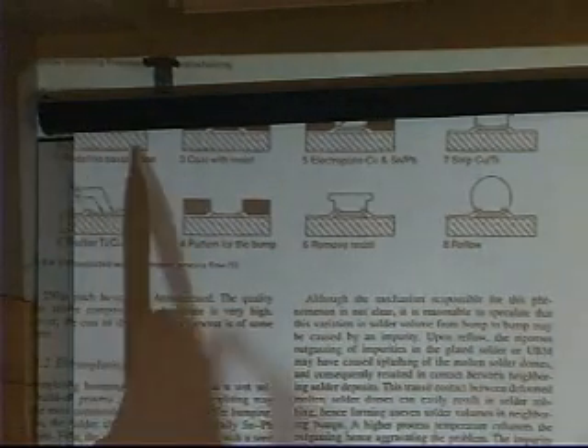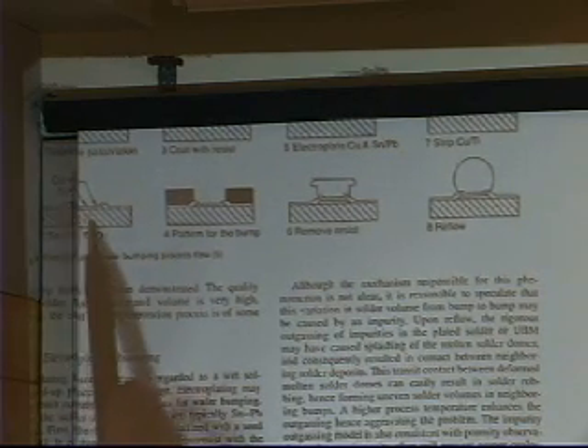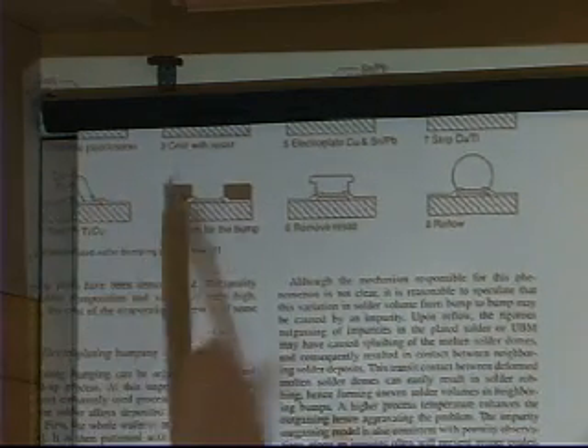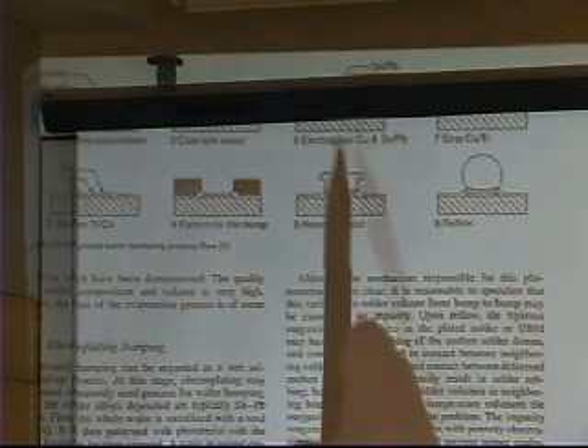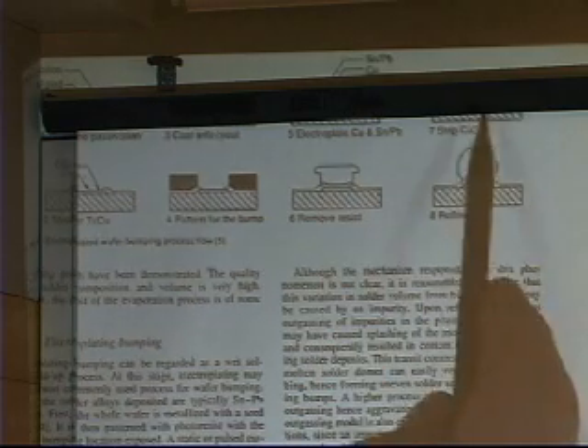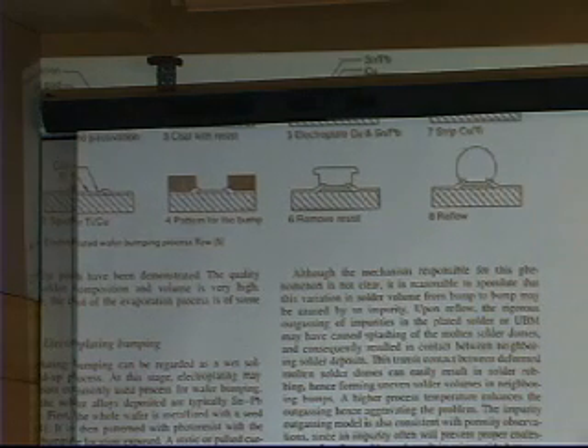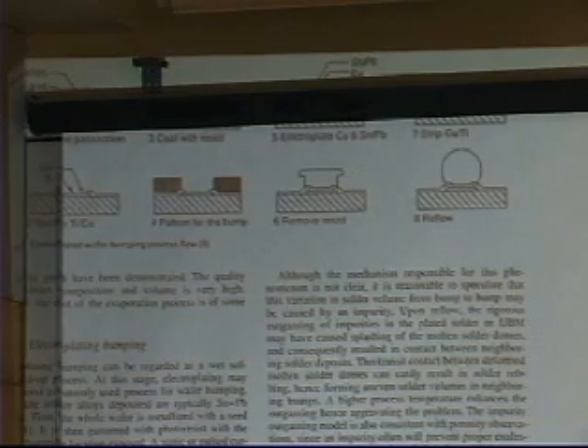Actually, no, I'm sorry, they're going here. First sputtering titanium copper, and the reason they use titanium is so you don't get diffusion in there. Coat with resist, pattern for the bump, plate the copper, and then the lead tin, strip the resist, and then you reflow it, you just melt it, and it will naturally form a nice spherical ball. We'll talk later about why. Okay? So that's how you make a solder bump.